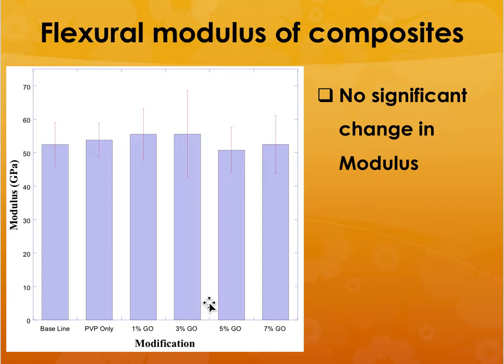But surprisingly, what we found is that when you start adding these nanoparticles, it does not damage the elastic modulus of the composite material itself. So it means that you get improvement in toughness without damaging the stiffness and strength of the material.